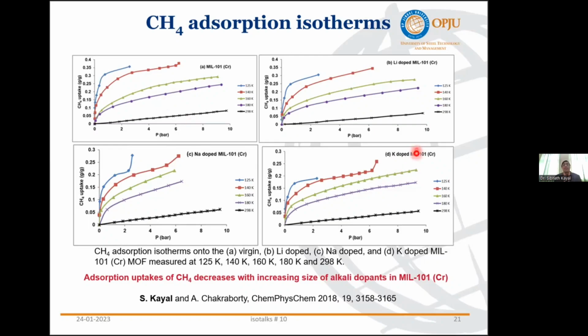So from this study, we can conclude that the adsorption capacity of methane gas decreases with increase in dopant size. Lithium, sodium, potassium ions are considered alkali ions. Whenever you go from lithium to sodium to potassium, their atomic size or ionic radius increases, and these atoms or ions occupy the interstitial sites of the MOF structure. So it hinders the overall occupation by the methane gas. That's why the adsorption capacity decreases with increasing size of the alkali dopants.